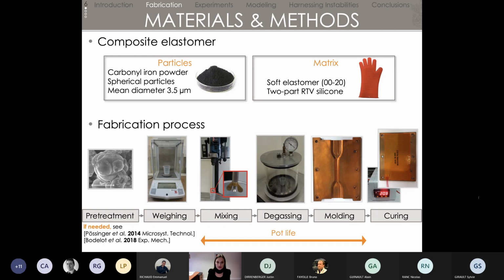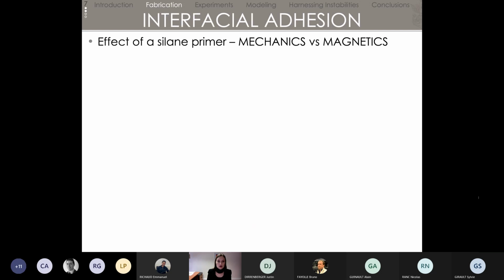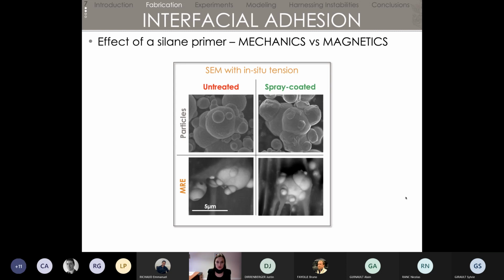About the pre-treatment: when we were putting hard particles inside a really soft matrix, the first thing that we thought about is that we would have debonding, because, you know, hard particles inside a soft matrix. So what people usually do when putting hard particles inside a soft matrix is treat them with a silane primer. It's just a chemical that helps enhance the bonds between your particles and your matrix. So that's what we did. I have here some SEM pictures. At the top left, you see normal particles. On the right, they are treated, so they have a coating of that silane primer.